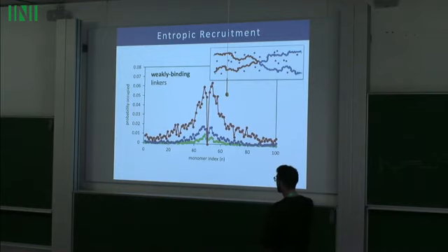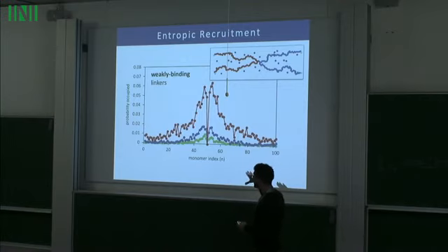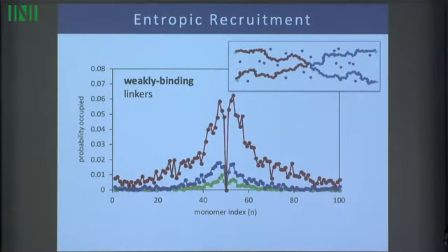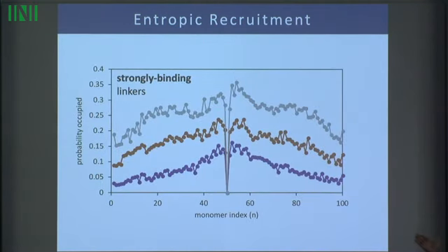And these are for somewhat low binding strengths, low binding enthalpies. And so the green is very weak, the red is a bit more moderate, and you actually see a very clear clustering, that there's a preponderance, quite a substantial enhancement of probability of finding a bond quite close to the permanent crosslink. These are for free polymers, and they have excluded volume and everything like that. Okay. If I go to stronger binding linkers, then I start to lose this effect.